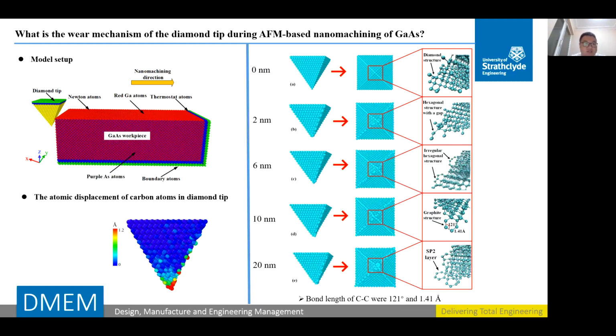With nanomachining advancement, an irregular hexagonal structure was shown at 6 nanometer. Then, a complete hexagonal carbon cycle structure occurred at 10 nanometer. Subsequently, the measured bond angle and bond length of carbon were 121 degrees and 1.41 angstrom respectively. This result is very close to the graphite hexagonal lattice structure.